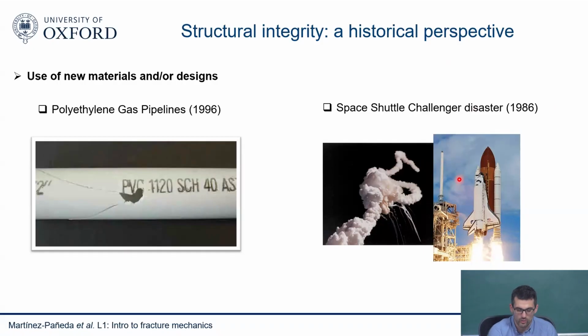They knew what they were doing. But the problem is that one of the gaskets that they were using was tested under room temperature conditions, and it became much more brittle under low temperature conditions. And this gasket was exposed briefly to low temperatures, but for a sufficiently long amount of time that it caused embrittlement and the fracture, and then this disaster. So even though we test things carefully, every time we deal with new technologies, we need to think very carefully about what we do.